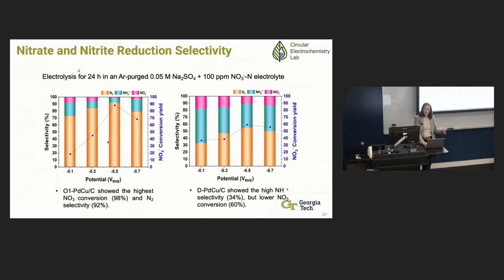And so again, I'm showing you selectivity data here. Now we looked at both nitrate and nitrite, and looked at the product selectivity. Here again, looking at nitrogen, ammonia, and nitrite. And essentially, for the most part, we either want nitrogen or we want ammonia. We don't want both. And we don't want nitrite, because we want all of whatever we put into our system to react.